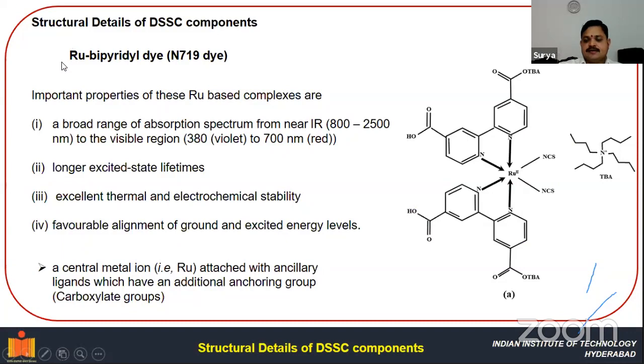In the structural details, the kind of dye that we have used in our device is N719 dye, and it has a broad range of absorption spectrum from 800 to 2500 nanometers. As I mentioned, a semiconducting material will have a very narrow absorption spectrum, so it cannot absorb the entire light that we receive from the sunlight. Instead, if you use a dye, it can absorb the maximum range of the light that we receive from the sunlight. For instance, N719 dye absorbs the light in the infrared range, 800 to 2500, to the visible region, 382 to 700 nanometers.